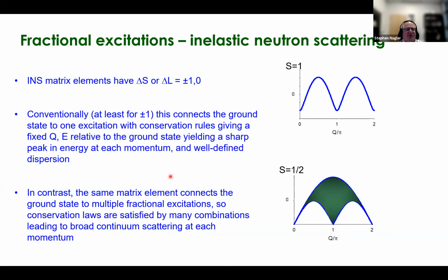Now, what I mean by a fractional excitation is something where the intrinsic excitation does not have a spin of 1 or 0 relative to the ground state. So if I measure a matrix element with delta S equals 1 or delta S equals 0, if let's say the excitations are spinons that have a spin of a half relative to the ground state, I will be sampling a state that has multiple excitations. So the conservation laws are satisfied if I have many combinations of these elementary excitations. And this gives me, for each wave vector, a broad continuum of scattering.